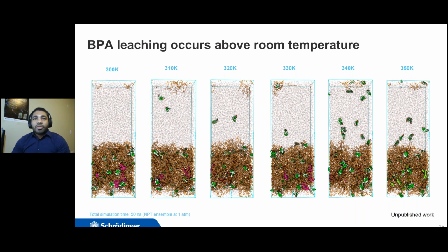So that's one of the reasons you might be thinking, why is liquor stored in glass bottles and not plastic bottles? This is the reason why. The ethanol typically accelerates the leaching behavior of any of the plasticizers that are present in the plastic bottle. Right. So this is a nice way of looking qualitatively at how the leaching occurs.